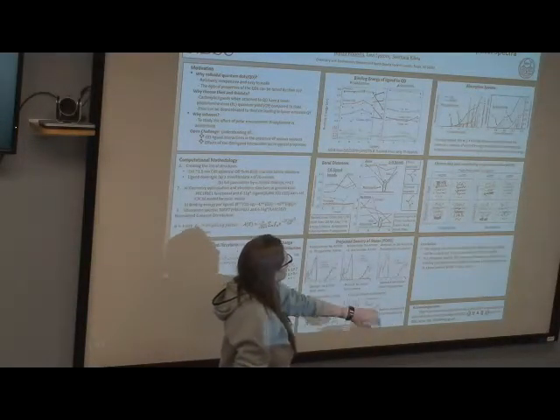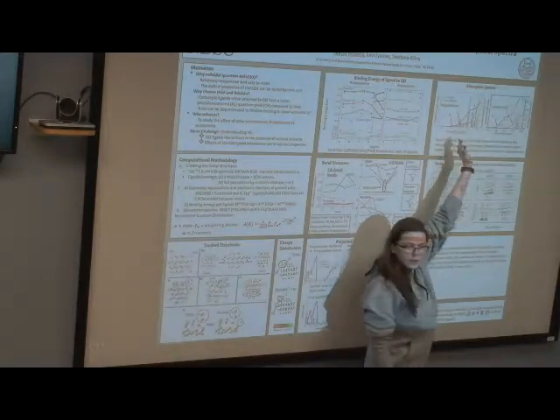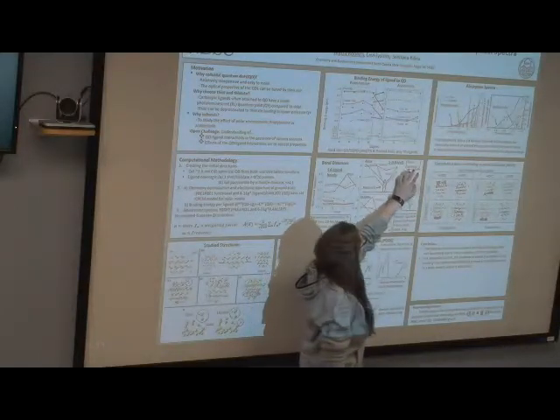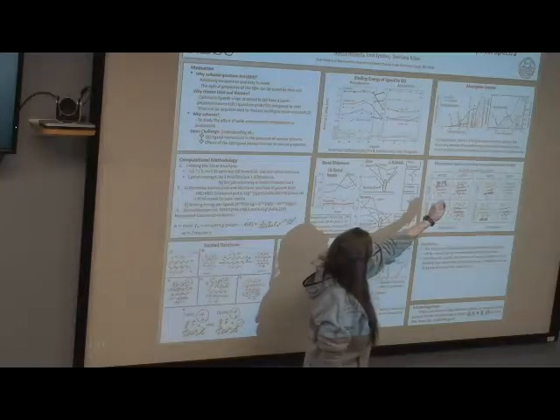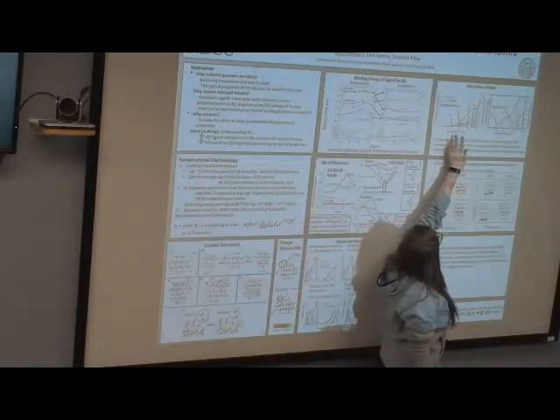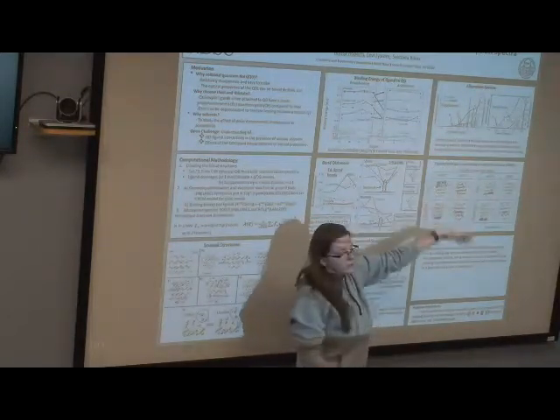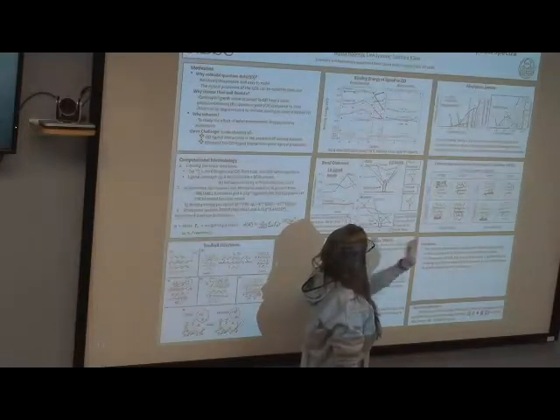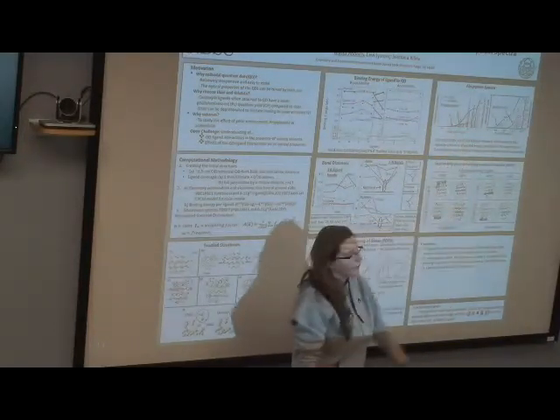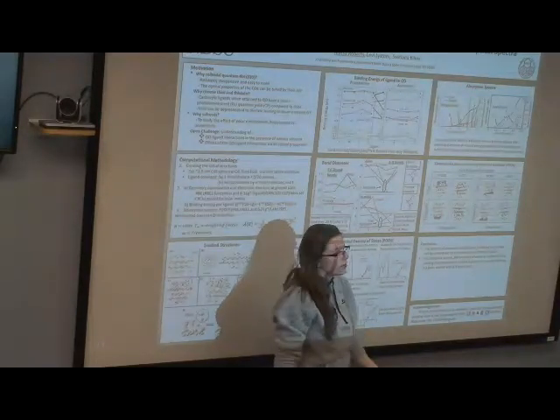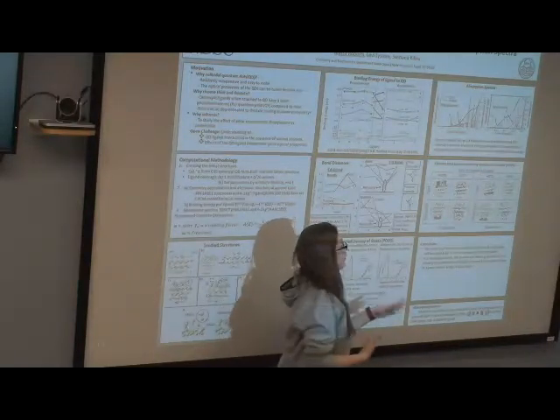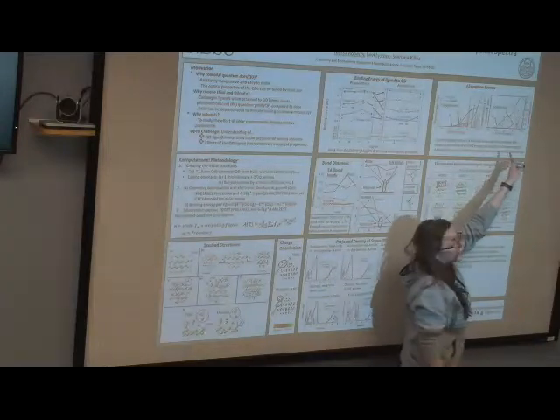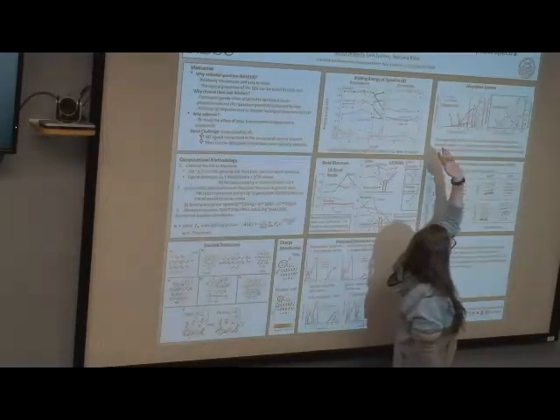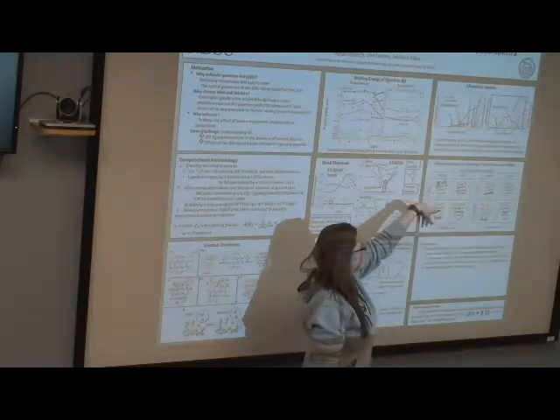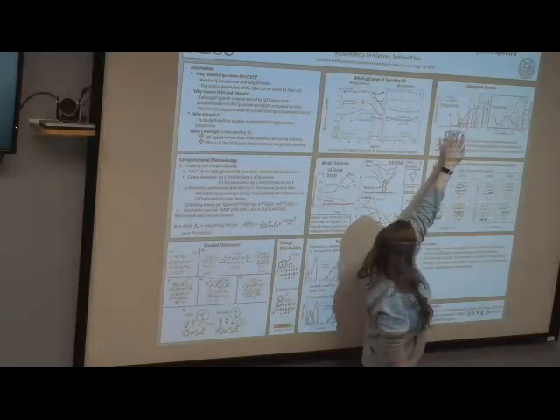Okay, and then the absorption spectra, so for propylamine, you can see that the first, would it be proper to say transition, or what is the correct word? Optical transition? Yeah, transition would work. Okay. The first transition is further, requires less energy, but is a very dim transition or has a small oscillator strength. Whereas the first transition for the thiol is relatively bright compared to the thiolate. So that shows that the optical properties of thiol are better than the optical properties of thiolate. But for acetonitrile, you can see that the thiolate is pushed significantly further back, but the oscillator strength is brighter than the first transition state there.